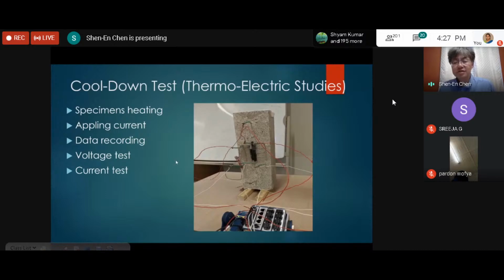And then we are trying to correlate the thermal properties, which is the temperature change versus the resistance change in the concrete material. Again, the same technique: we apply currents through the material and then measure the change in voltage. And at this juncture, we also realized that there is another component to it, which is that the current is also changing through the material. And so in this particular test, we measured both the voltage and the current change.